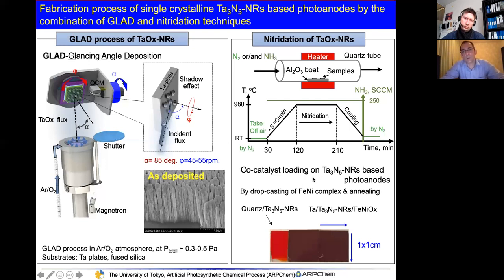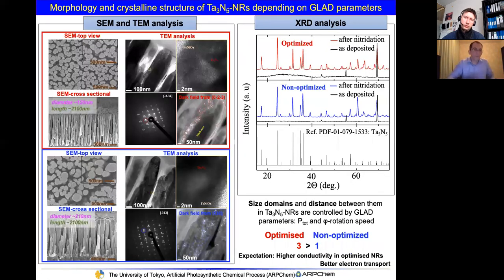And then the co-catalyst loading on the Ta3N5 nanorod based photoanode. And this is the picture of the fabricated photoactive material. As you can see, this material has a very nice red color because the band gap is about 2.1 electron volts. Of course, there are many parameters to control the nanorod quality, because the photoelectrochemical performance depends deeply on the diameter of the nanorod as well as crystallinity. I will explain why.